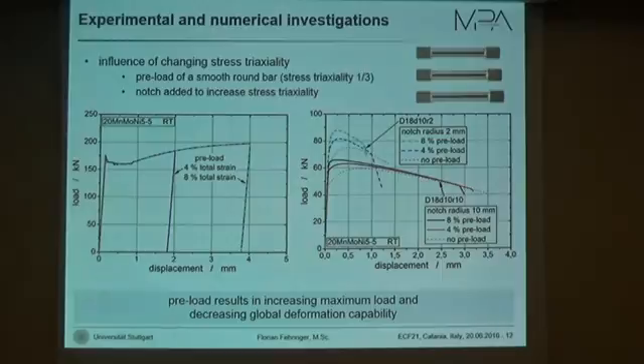As I already said at the beginning, the loading path might have an influence on limit strain, so we did first tests on the influence of loading paths with a 2-step test where we changed the stress triaxiality during the test. We first had some simple smooth round bars which we pre-strained to a total strain of 4, respectively 8%. Afterwards, we took those specimens back to the workshop, added the notch to it, and so increased the stress triaxiality. On the left you can see the load displacement behavior during the preload, and on the right we have the load displacement behavior for the notched specimen, with 2 different notch radii: notch radius 2 millimeter and notch radius 10 millimeter.